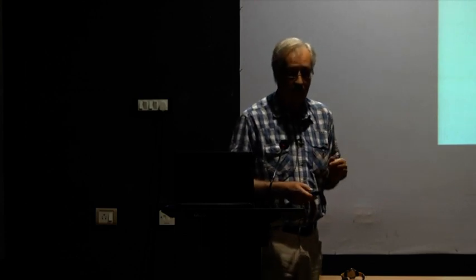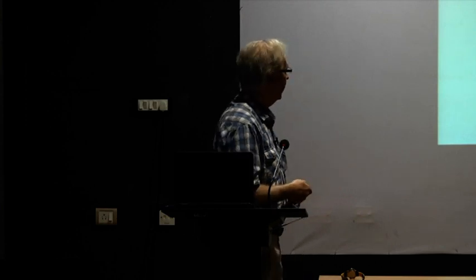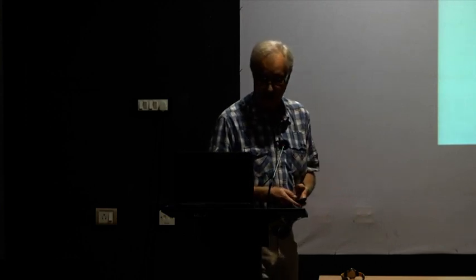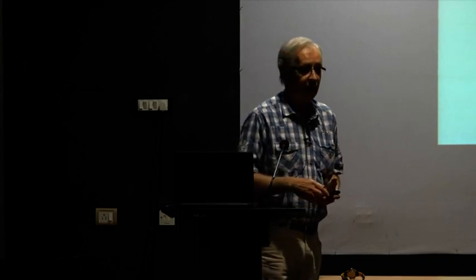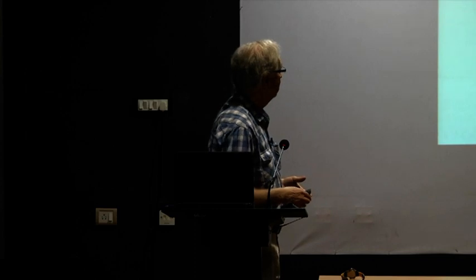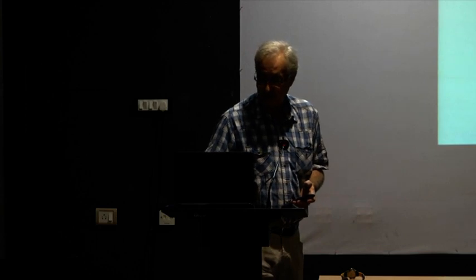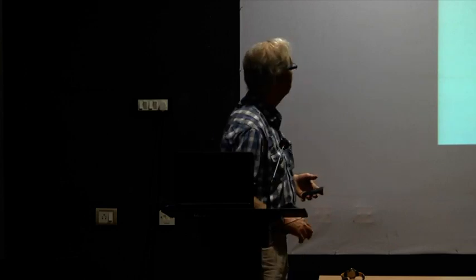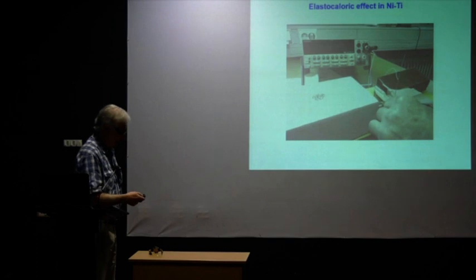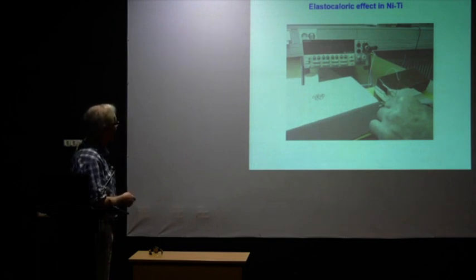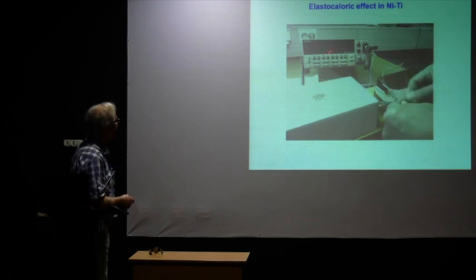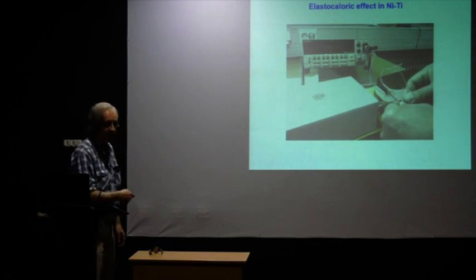And nickel titanium has one other interesting aspect, and that is the fact that this is a very good elastocaloric material. Now, this is what I wanted to show you yesterday, but it didn't work, so I'm showing it to you now. I think all I have to do is just click on that, and yes, it's working. You may faintly see the numbers here. They're changing. This is about 19.6 degrees centigrade, and now I bent it, and it goes up to 27 degrees. I don't know whether you can see it. So that was 19, it's 20.